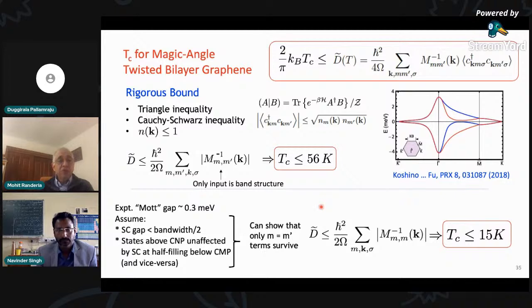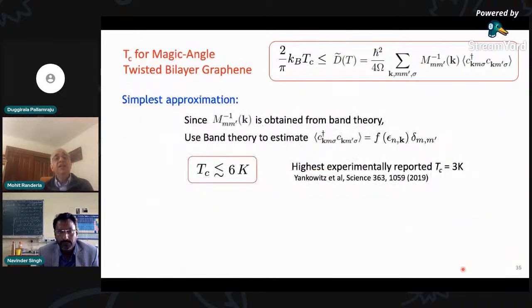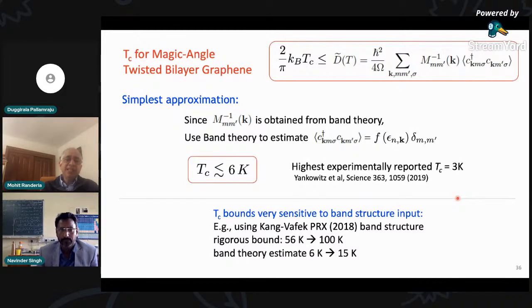Then we can say, okay, I don't want to be a mathematical physicist. I want to be a real physicist. So I can make some assumptions about what's going on, that the superconducting gap is very small and certain states are only impacted, and I can make a TC estimate of 15 Kelvin. And if I just use band theory to estimate this density matrix, which is here, I get a TC estimate of 6 Kelvin. This I wouldn't call a real upper bound. The real upper bound was 56 Kelvin. And the highest reported TC is 3 Kelvin right now in this system. So the TC bounds are very sensitive to band structure, but that's at least where we are.